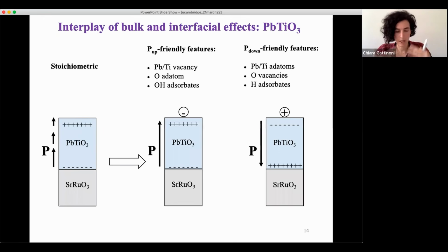And we did a number of density functional theory calculations for this, and we found a couple of things. Lead titanate has a critical thickness of 7 unit cells, and even at 7 unit cells, the polarization is not that robust. It will be robust at an electrode, but it goes to 0 towards a surface.